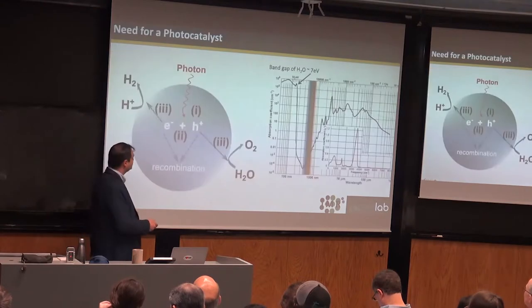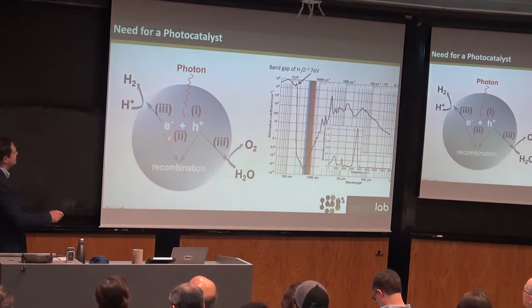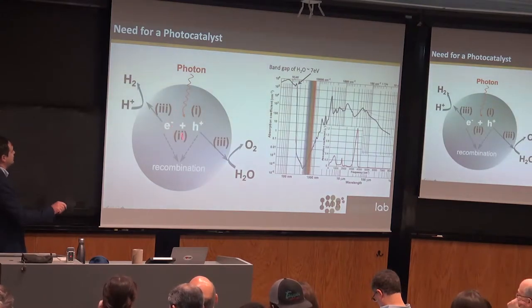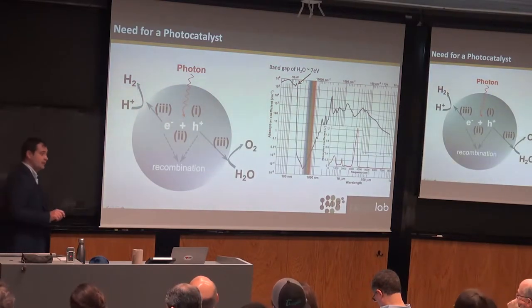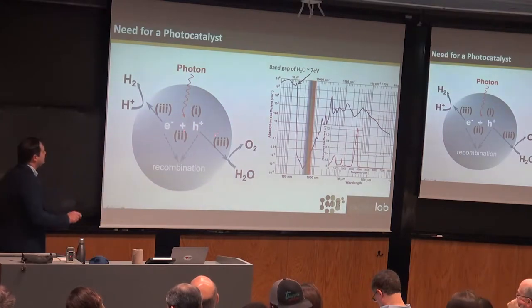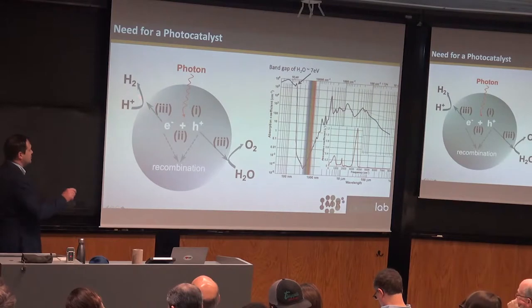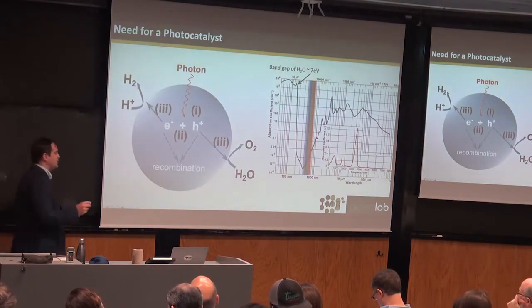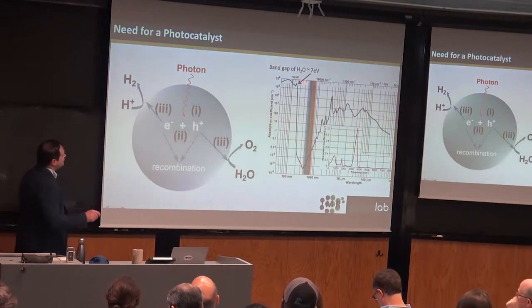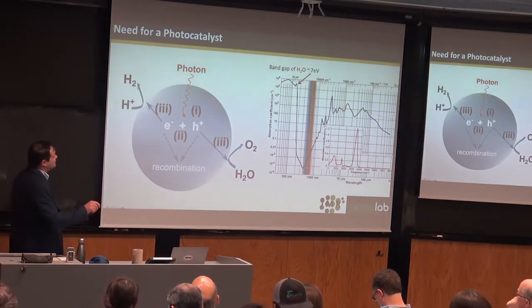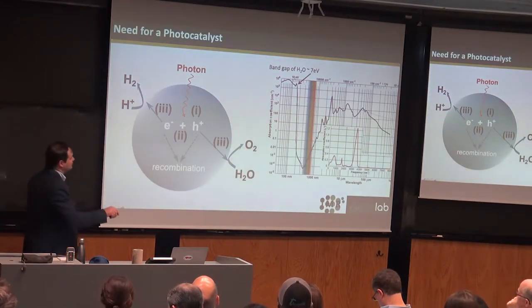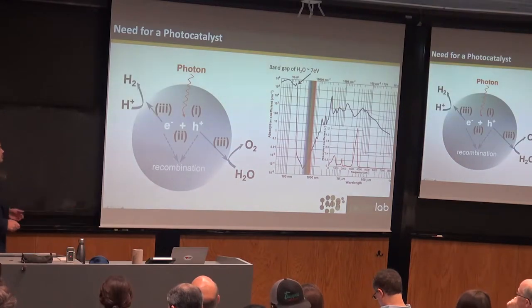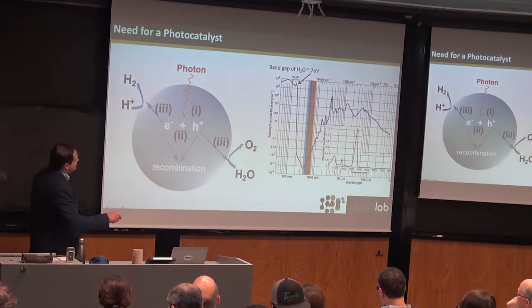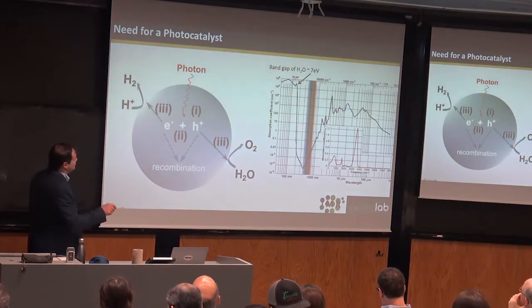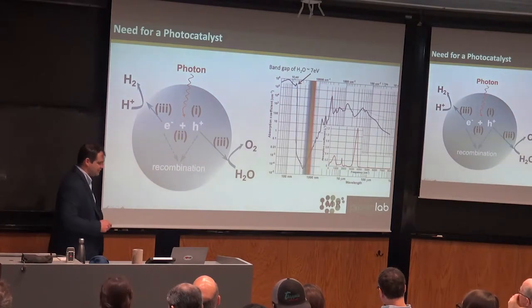I'm almost going to get to the co-catalyst bit, but the main thing we want to do is take visible light, generate an exciton, split that exciton, and transport it at energies relevant for the redox reactions at these two sites. Okay? So the key element in this is the exciton separation and the energy with respect to these redox levels. So that's the critical component that we'll be focusing on. And the one thing to note is you need a photocatalyst because water can be viewed as having a wide band gap material of 7 eV. For a lot of applications, we actually use deionized water as a very good insulator. And so we want to use visible light. So using a photocatalyst is critical for splitting water.